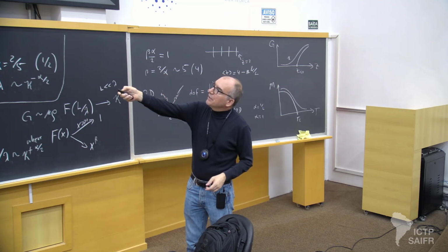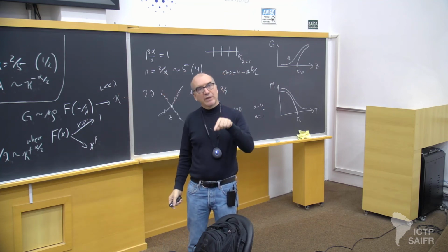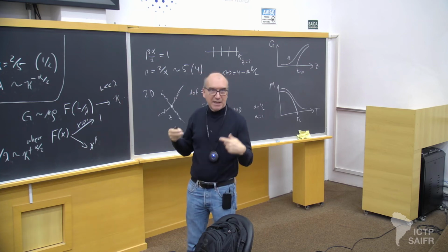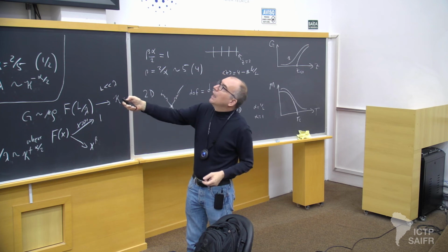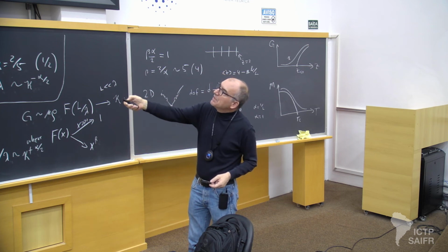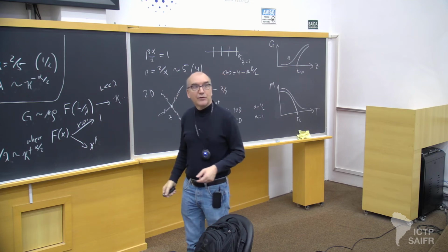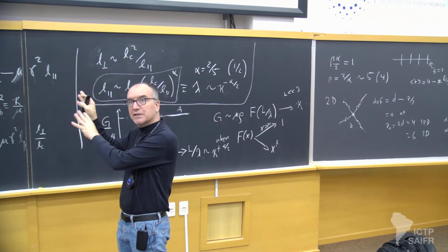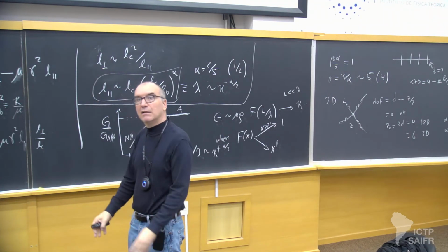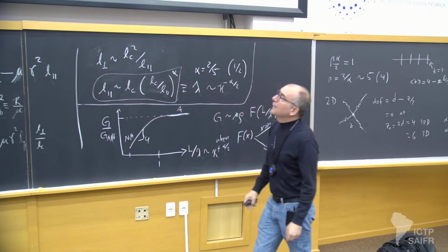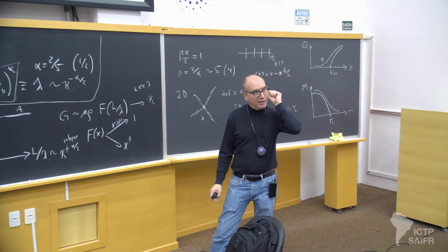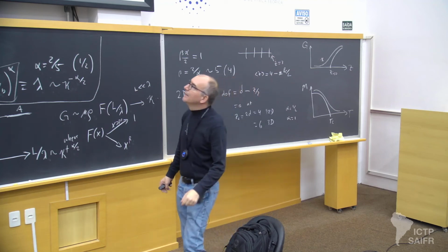So there is another transition, and it's rigidity percolation with bending. And so that's what's happening at this lower point. We studied both in this paper. That happens at this lower point, and notice that there's peaking fluctuations there too. So they're both critical, and I'll return to more of this next time with finite strain to see what happens. That's going to be very important for understanding the nonlinear mechanics of collagen I started with, the earlobe pulling experiment.